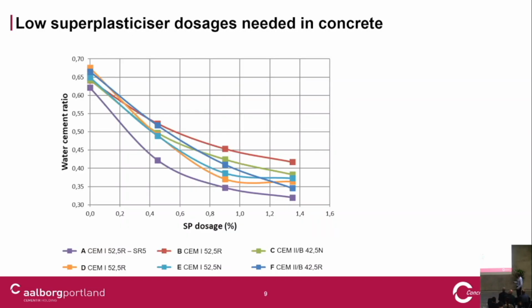And we have tested that effect in the laboratory. This graph shows water-cement ratio in a concrete, and here it shows the dosage of superplasticizer. These are different cements, and this violet color is the Aalborg White from Denmark. The others are also white cement.